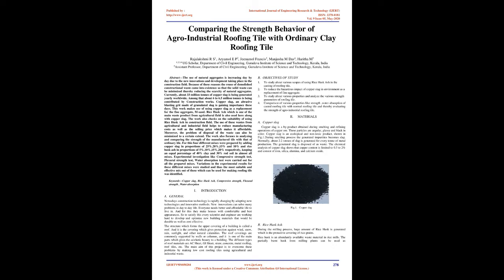The work also focuses on analyzing and comparing the strength of the manufactured tile with that of ordinary tile. For this, 4 different mixes were prepared by adding copper slag in proportions of 25%, 20%, 15%, and 10%, and rice husk ash in proportions of 5%, 10%, 15%, 20% respectively, keeping an equal percentage of 40% clay and 30% red soil in almost all mixes.